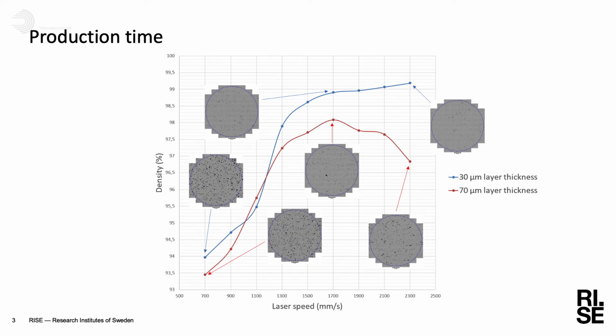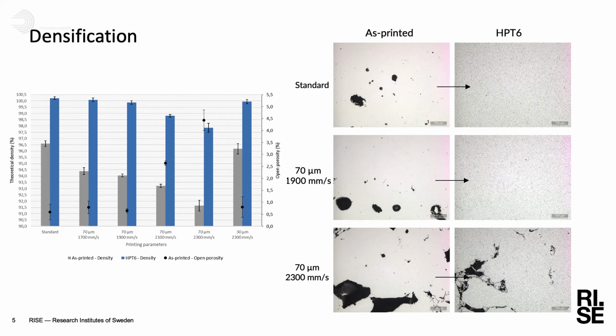Okay, so if you can increase the speed so much, Sebastian, what's interesting then is the quality of the parts after this high-speed process, including the high-speed printing and the hot isostatic pressing with heat treatment included. What's the quality like? So when increasing the speed, we can see that we always get the maximum for the density, where we get the best density. But for the fastest laser speeds, we can see that we have a decrease in the density. So we are as low as 95-96% density, which is not what we want to have. So when introducing the hipping, we can close them and get a fully dense part.